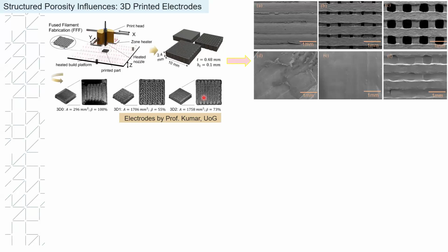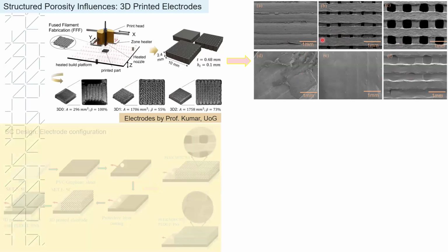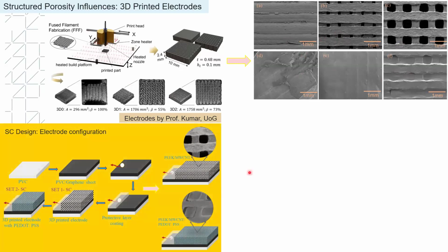For example, we have different 3D printed electrodes, where we create the porosity by using 3D printing technology. You can see from here that in the same image, there is a bulk sample without any pores, and then we create small pores and large pores, and then we coat this with a conductive polymer also. And then we used this for an electrochemical capacitor application.